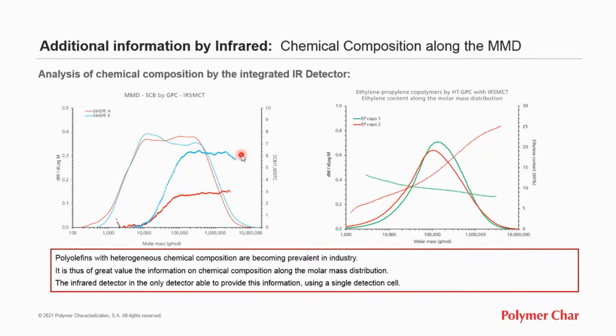Those small amounts of short chain branching can be quantified with infrared, and the different levels can be related to the final product mechanical properties, particularly the environmental stress crack resistance.